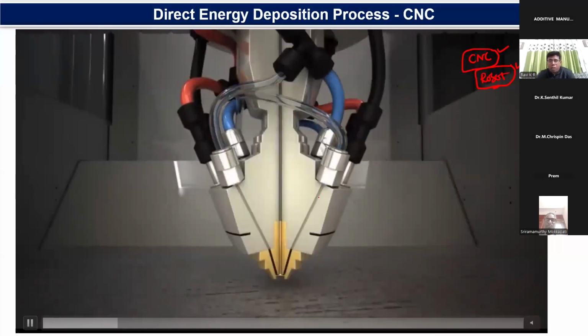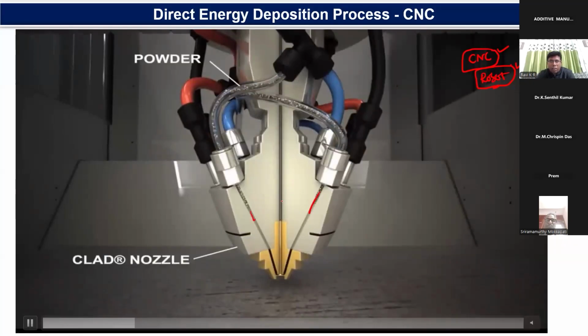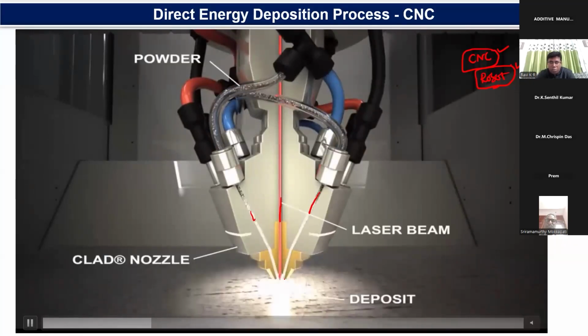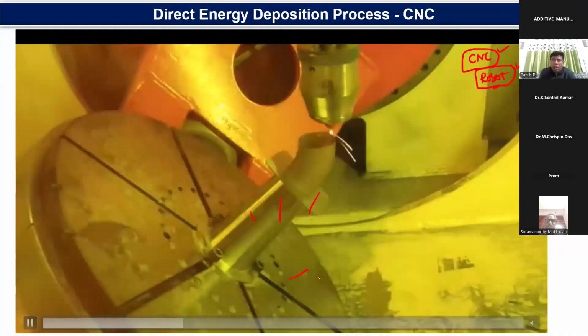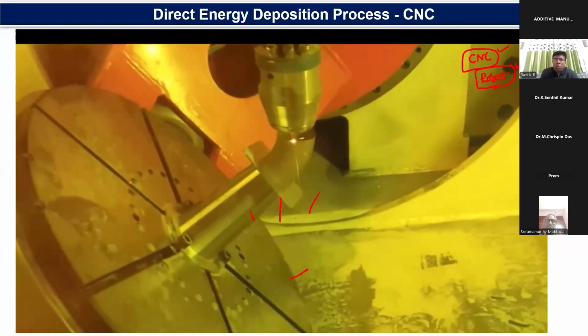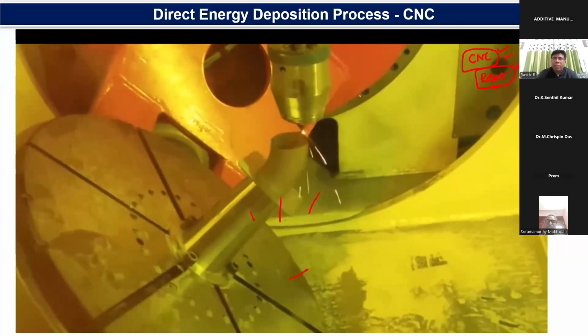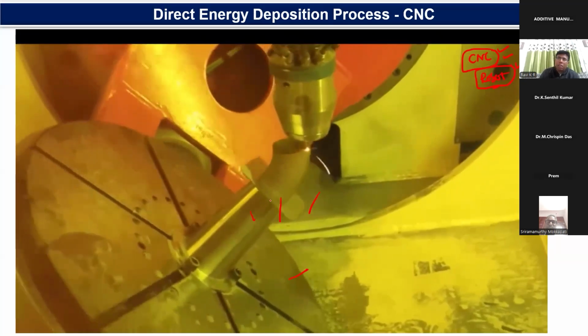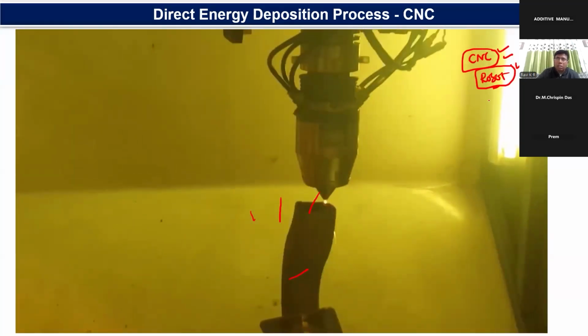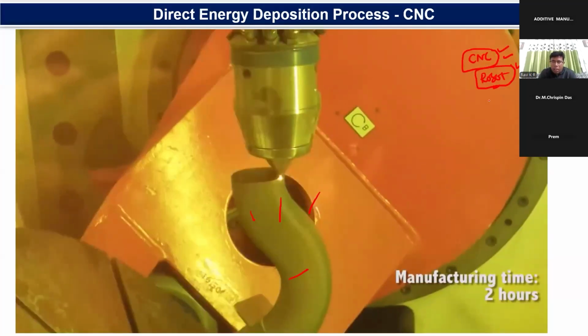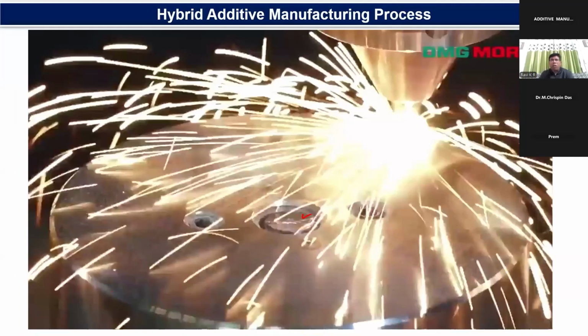In this system, the powders are fed through the coaxial nozzle and the laser comes from the center. The laser will melt this powder. Now the whole head will start moving depending on the CAD file that we are giving to the system. This whole motion of the laser head and the substrate is controlled by the 5-axis CNC. In this 5-axis CNC system, you have 3 axes on the top and 2 axes on the bottom. On the other hand, in the robotic system, which I'll discuss in the next slide, you can have a 5-axis, 6-axis, or 8-axis robot, depending on the features that we want to have.